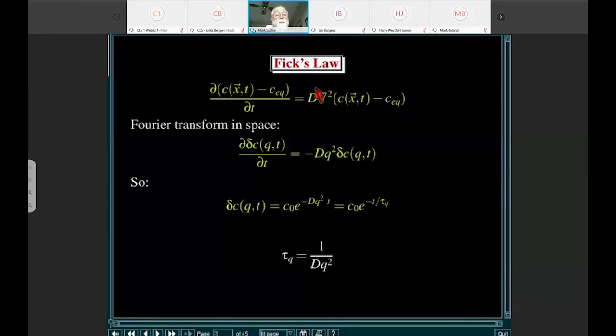Grad squared of the diffusion equation becomes a Q squared in reciprocal space, which is what we measure with diffraction. And so what we can see is the rate of change of the fluctuations in the material depends on the diffusion, and it depends on Q squared. We can actually solve this linearized diffusion equation very easily, and what we see is that the concentration fluctuations depend exponentially in time.